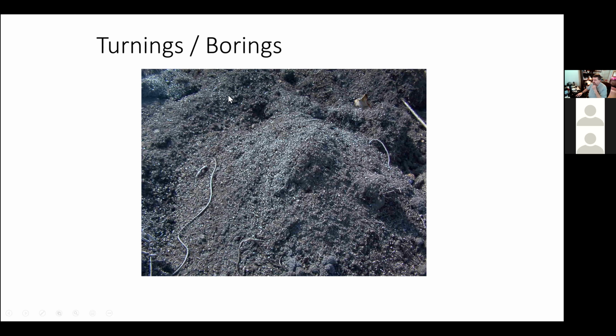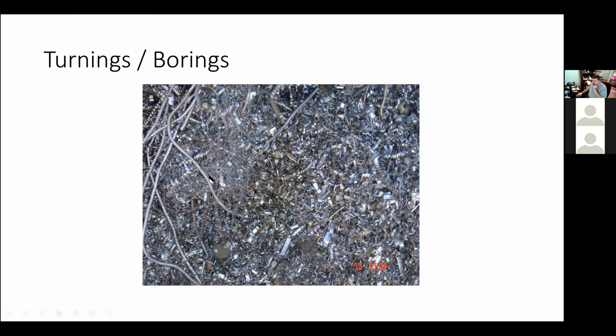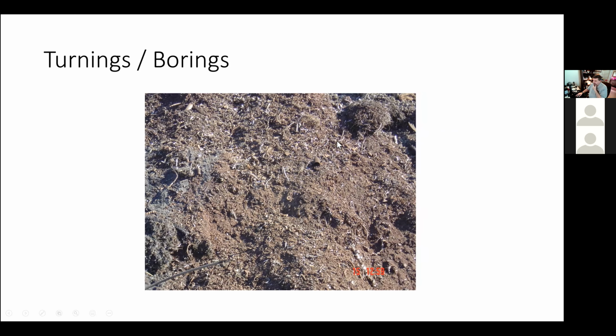Downside of some of these materials is that they sometimes contain a lot of oil. Now, nowadays, a lot of operations are trying to move towards water-soluble lubricants in this type of processing, so that we don't have a lot of oil and grease in these materials, because that does pose a problem when we use them in the furnace. So they're trying to produce materials that are a little cleaner. But unfortunately, because those materials are so small, you have to use them up very, very quickly. You can't leave them standing around for too long. If they're standing out in the rain, after a few days, they'll end up looking like this.